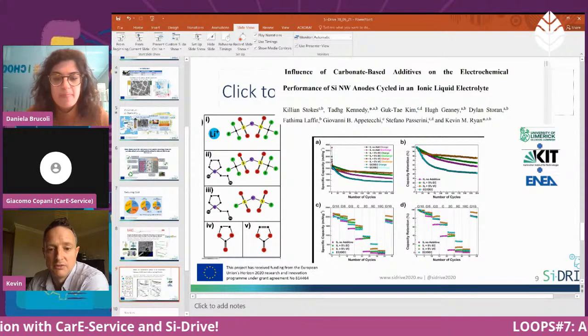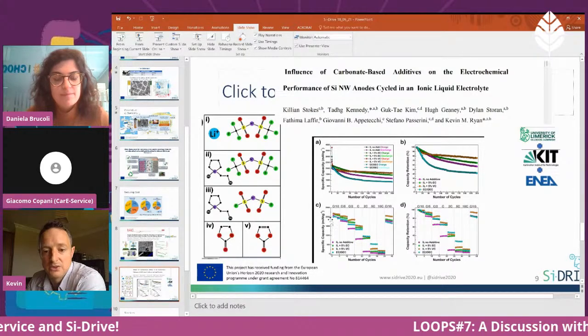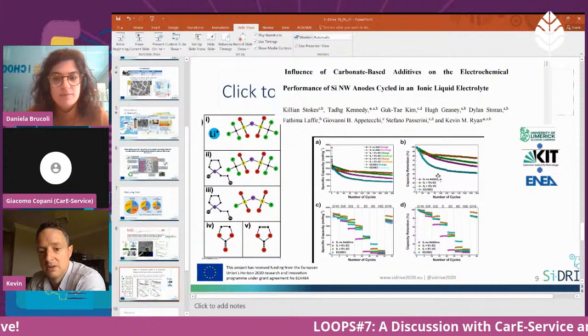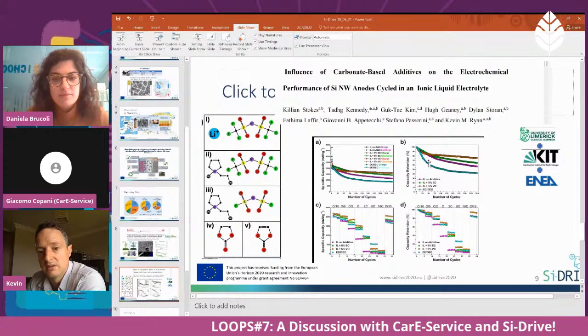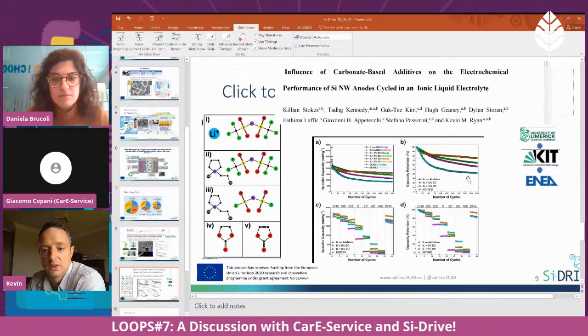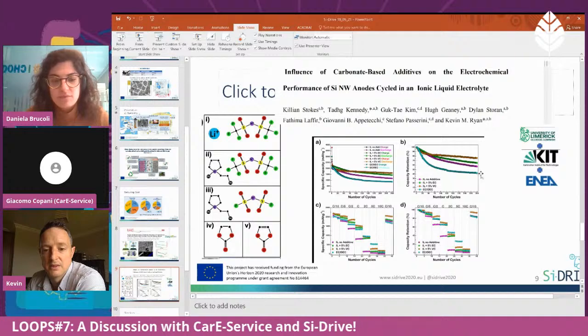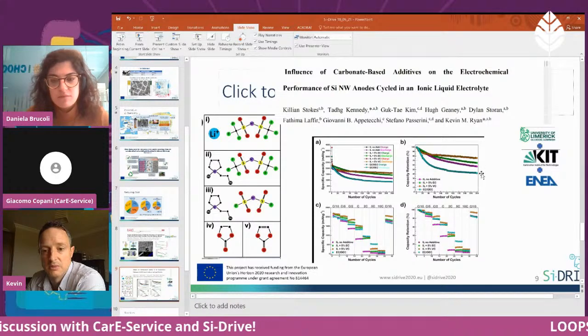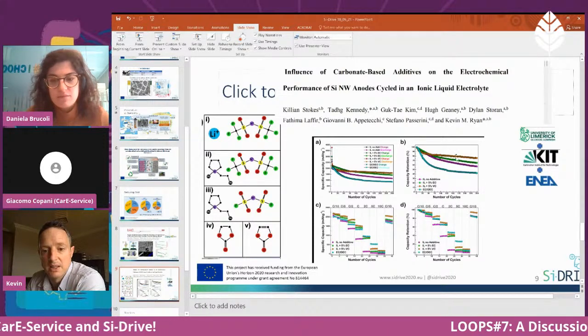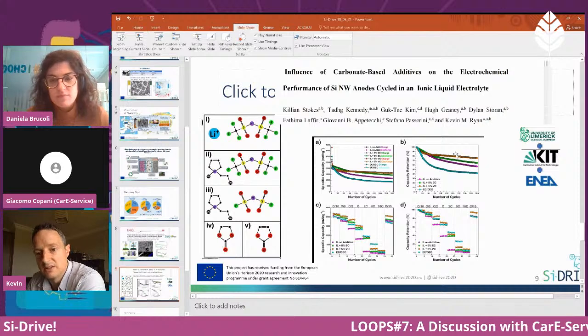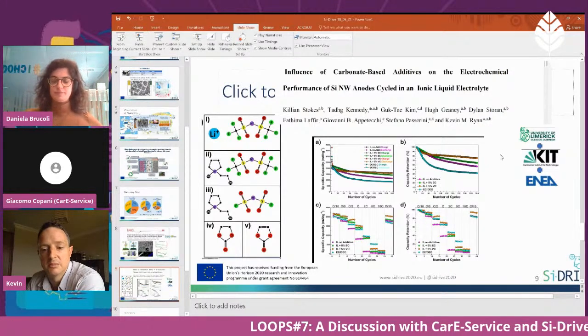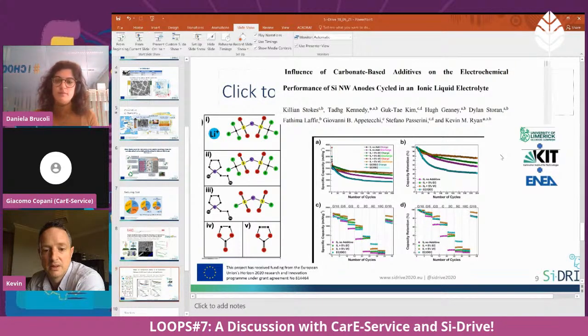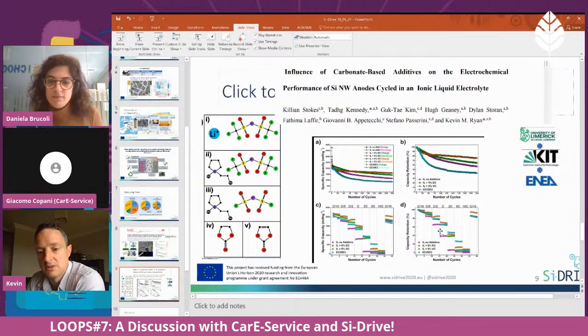So if you look at B here, I don't need to go through all these in too much detail. We're comparing the no additive situation, where we can see that there is very, very poor performance. And then when we have the 5% VC, we get a stable SEI layer, so we get a much more stable capacity retention.